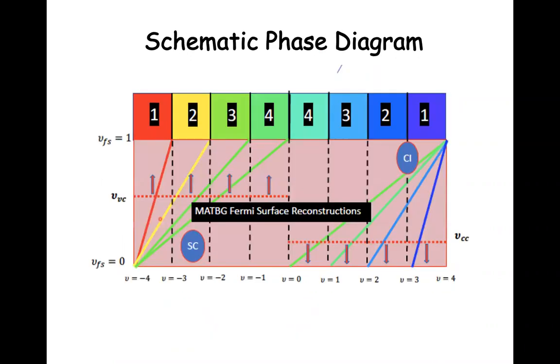And so what is going on, I believe, and I think this is probably the picture most people in the field have, is that as you make holes in the valence band, the bands are very narrow. You're approaching a region where the density of states is even higher, and the system reorganizes by emptying 2 of the 4 bands, and then it starts emptying them again. So these are jumps which are huge Fermi surface reconstructions, which completely eliminate some pieces of Fermi surface and shift the total carrier density by 1.